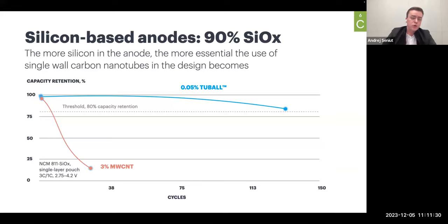In this case, it was also 0.05% of TUBALL used as an additive in the battery, versus 3% of multi-wall carbon nanotubes. Yes, the overall cycle life is smaller, but this is 90% silicon oxide and lab tests. But you can see the difference in the performance, which can be applied and translated if you're developing your own battery with a silicon-rich anode, 30%, 40%, etc.